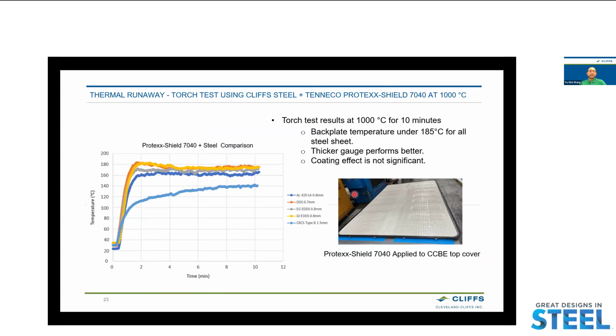As I forgot to mention, the previous test was conducted at 1500 degrees centigrade. This one is at 1000 degrees centigrade for 10 minutes. So it's a test of different combinations of different steel with different coating, different gauge with Protex shield 7040. As you can see, all the tests show excellent results with the backplate temperature no more than 185 degrees.